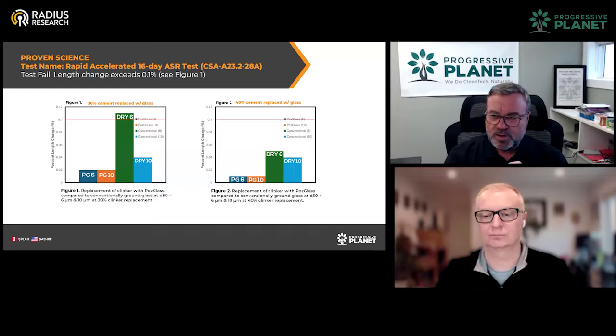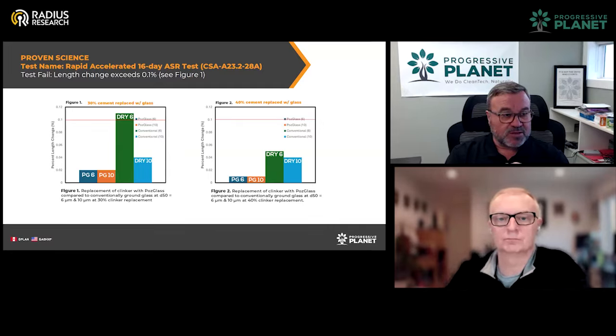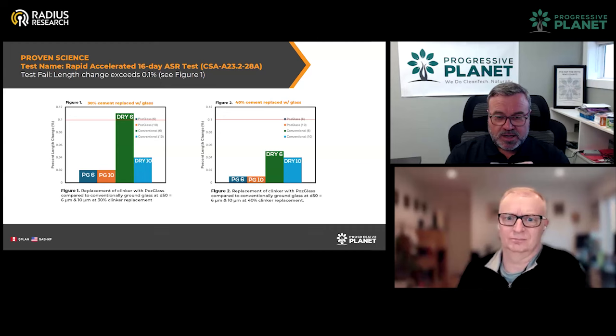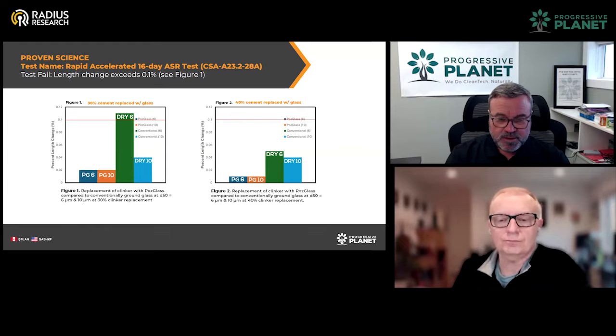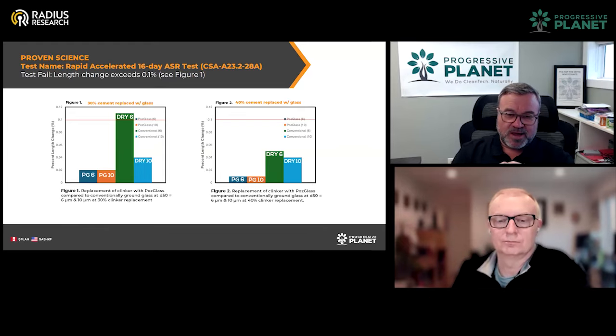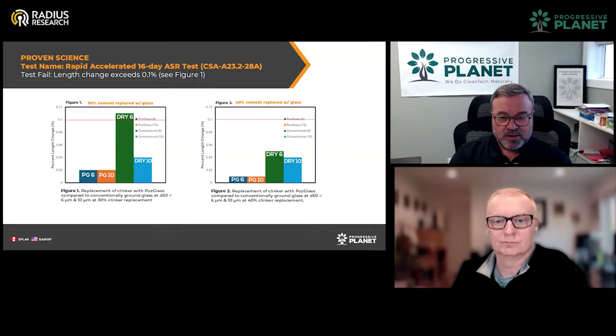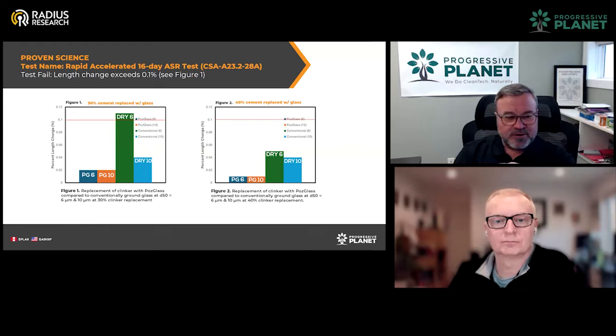Then in figure 2, we've done the exact same test, except we replaced 40% of the cement with the two forms of glass, the PozGlass and the dry glass. Now, if you look at figure 1, with the 30% substitution, you saw a 0.02% expansion on both the 6 and the 10 micron sizes. The 6 micron dry failed the test, and the 10 micron passed, but with substantially inferior results to the PozGlass.